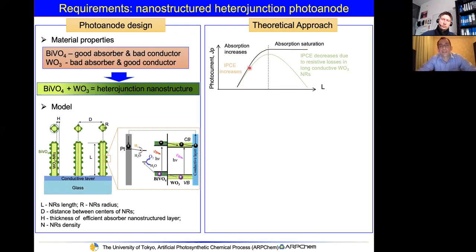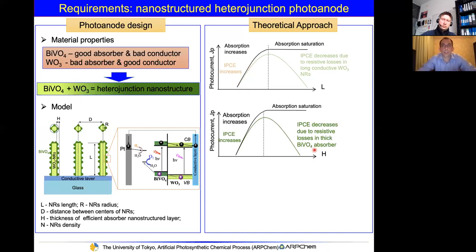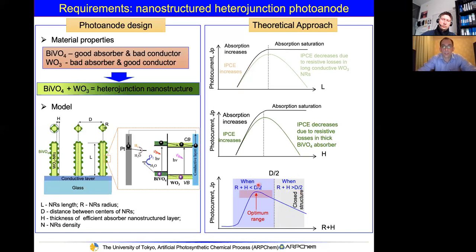However, if the material exceeds the appropriate thickness, the IPCE decreases due to resistive losses in the long conductive tungsten oxide nanorod. A similar scenario applies to the bismuth vanadate. Thus, looking at this relation, there is only a quite small window for optimization, where the material absorbs enough light, has very good charge separation ability, and enhanced surface area. To fabricate such materials, we have to precisely control nanorod diameter, density, and length, as well as bismuth vanadate shell thickness and material crystallinity.